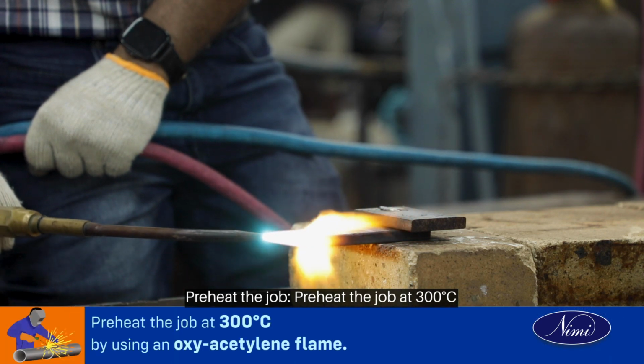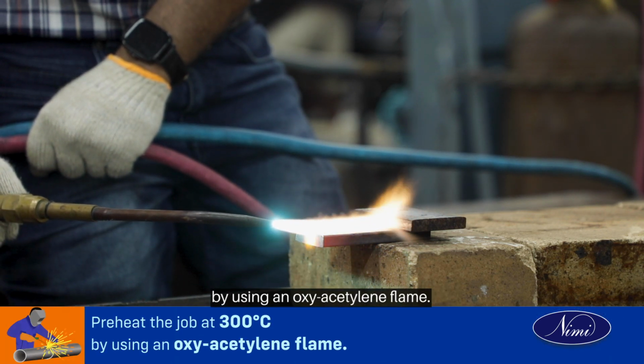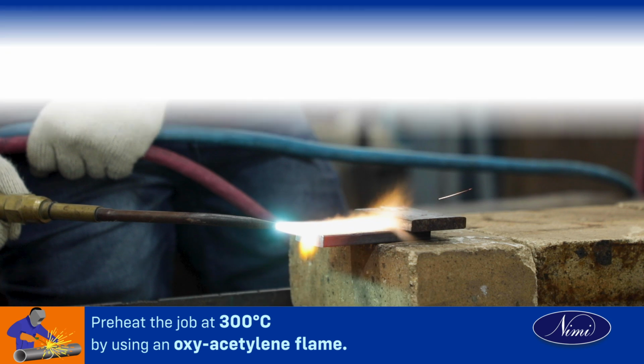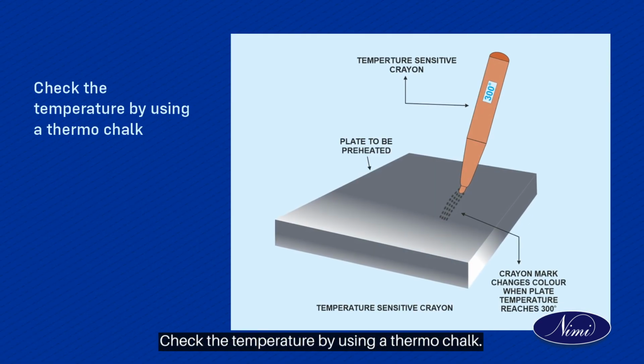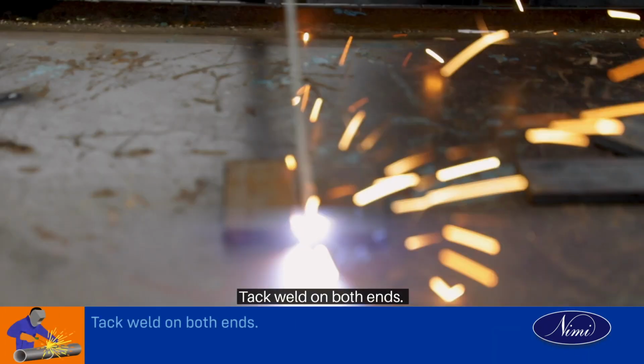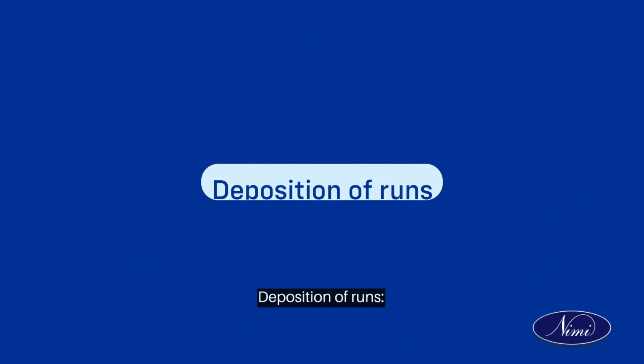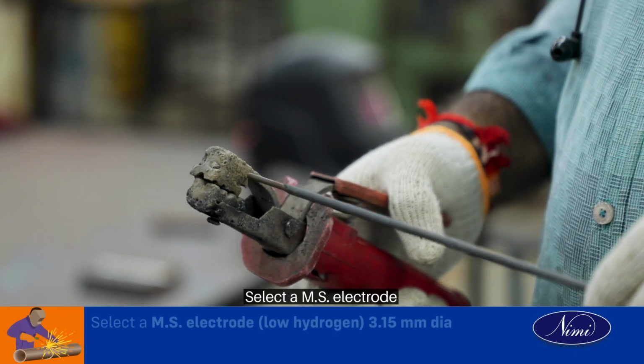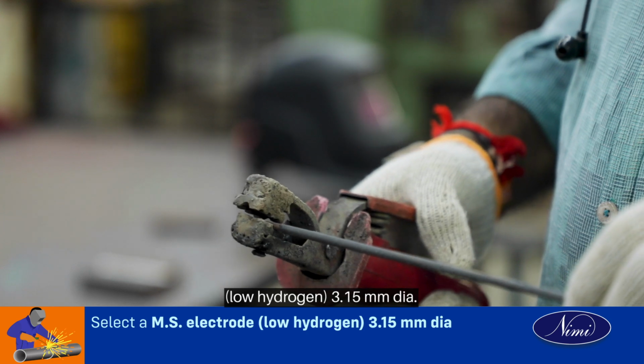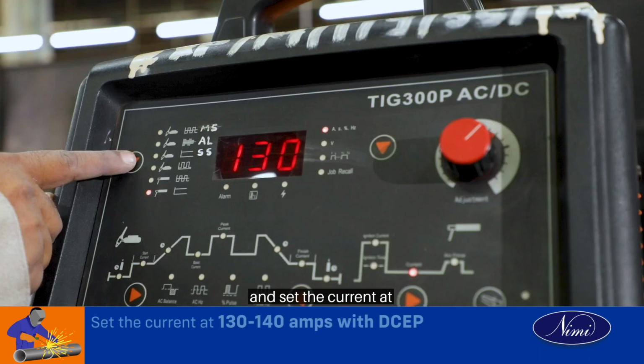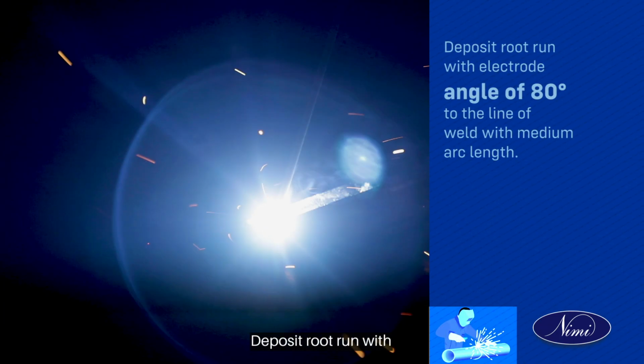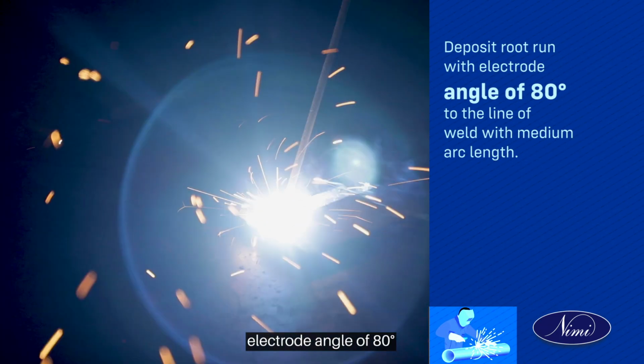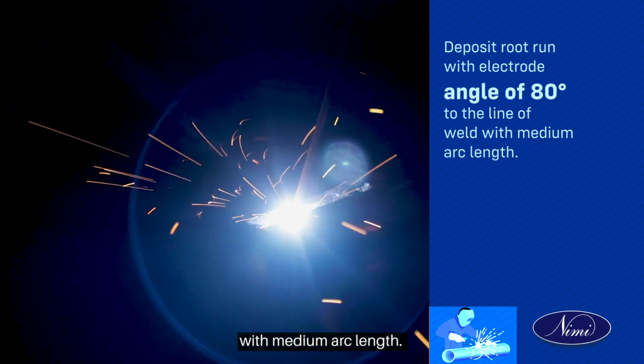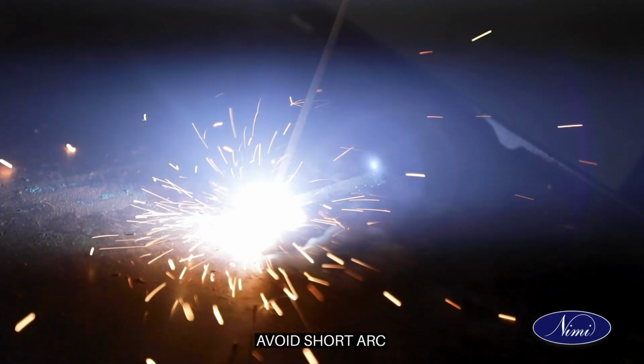Preheat the job at 300 degrees Celsius by using an oxyacetylene flame. Check the temperature by using a thermo chalk. Tack weld on both ends. Deposition of runs. Select a MS electrode, low hydrogen, 3.15 mm dia and set the current at 130 to 140 amperes with DC EP. Deposit root run with electrode angle of 80 degrees to the line of the weld with medium arc length. Avoid short arc.